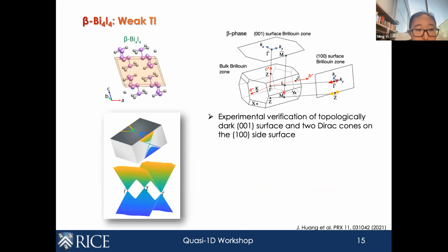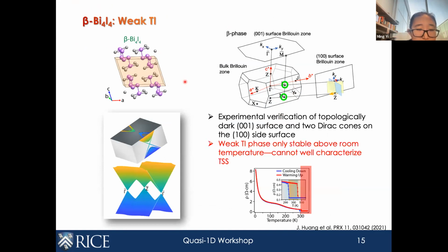So here, this is consistent with the expectation of two band inversions, which is consistent with the identification of a weak TI for the beta phase of bismuth iodine. This is all very nice and very cool. But there's one disadvantage of this, which is that everything I've shown you so far was taken above room temperature. That means that this is actually really difficult to characterize the details of topological surface states or use them or look at them in fine features.